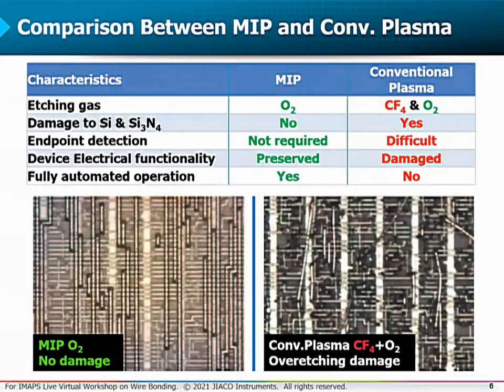This slide outlines differences between MIP and conventional plasma systems. The main difference is actually in the etching gases. Conventional plasma systems for decapsulation usually use a mixture of CF4 and oxygen, and MIP is an oxygen-only etching system. Due to the chosen chemistry, MIP will not induce any damage and over-etch silicon or passivation layers such as silicon nitride, which the conventional plasma decapsulation method will.